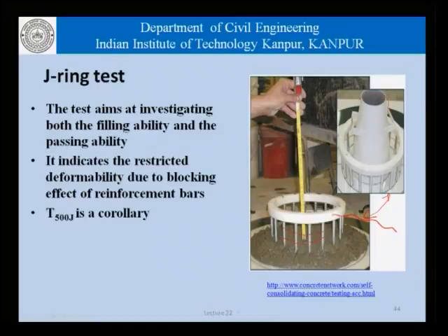So, the concrete is placed in the usual manner in a slump cone with this contraption on the outside, the cone is removed and then concrete is allowed to flow through this contraption. And as it flows through, it is not the free unrestricted flow as we would expect in the case of normal slump flow, but the concrete is flowing now through obstacles, and the measure could be in terms of again the flow that we achieve or the difference in heights inside and outside this barrier and so on.